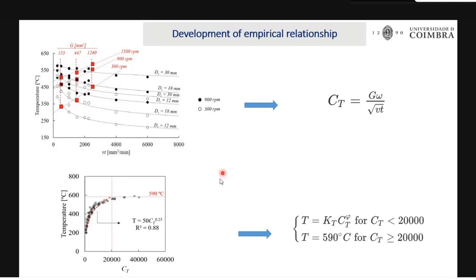Similarly, this is a curve, a non-linear one, so you have a different equation. The CT is nothing but the x, the exponent is nothing but the slope, and this is the coefficient for the fitting. It shows a good fitting because we have an R square value of 0.88. So these are the different aluminium materials, and in this way, this equation can be employed to calculate the temperature.